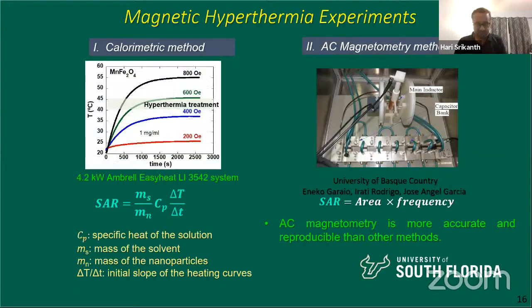Our data looks like this. This is temperature in degrees Celsius as a function of time. And as you can see, the hyperthermia window is 40 to 45 degrees Celsius. So for these ferrite nanoparticles, we can play around with the AC amplitude. Our frequency of the AC power supply is fixed. It's 325 kilohertz. I'll tell you why these numbers matter, but it's fixed. So we can only change the amplitude of the AC. So these are for different amplitudes. And you can select the best combination of frequency and field where you get the saturation right there at the hyperthermia window, because essentially you don't want to overheat it, right?